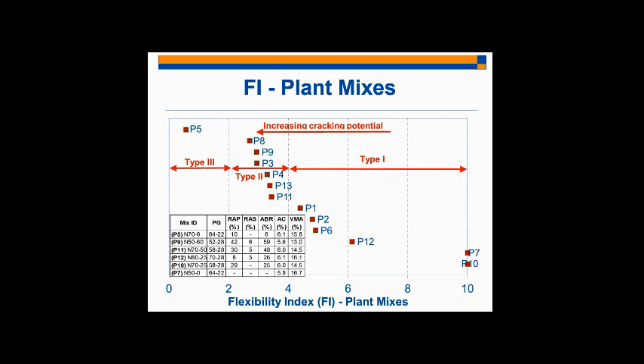What we've proposed, basically, is to subdivide this spectrum up into 3 different figures. And again, these thresholds will be further fine-tuned as our database of mixtures increases. So as we can better correlate to field performance and field cores and field surveying data, we can better refine and fine-tune these thresholds to result in more accurate prediction of performance.